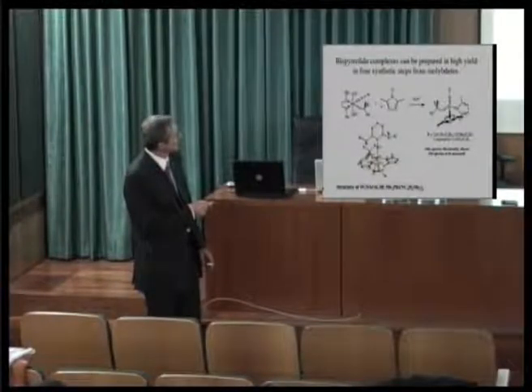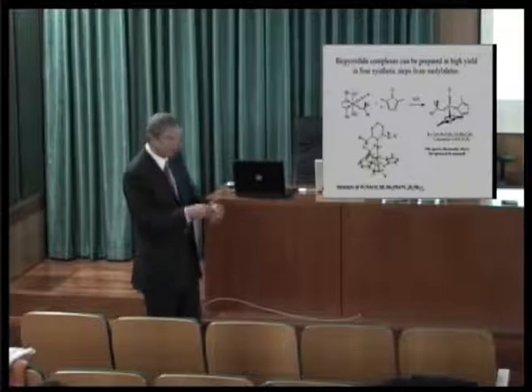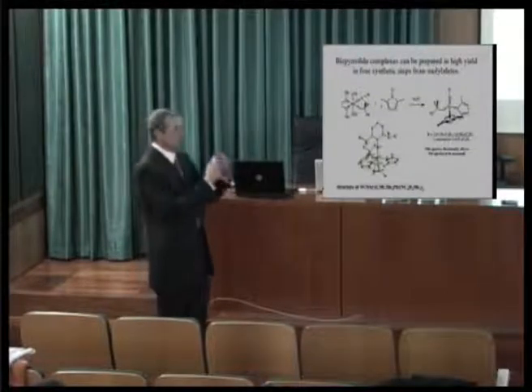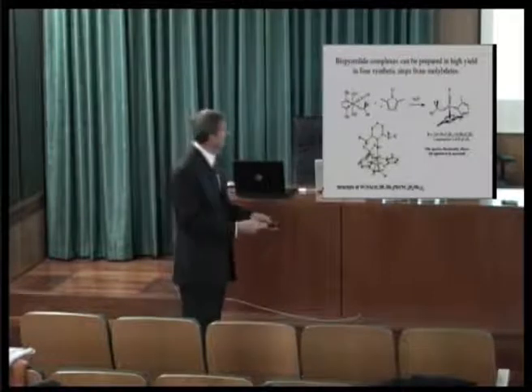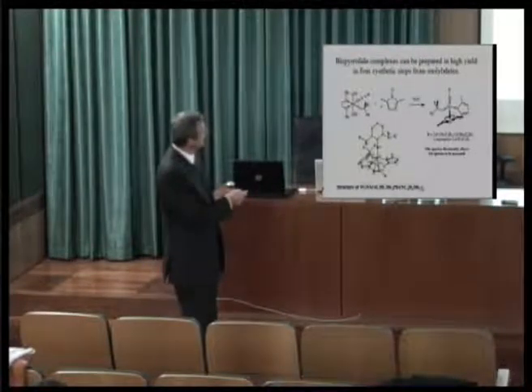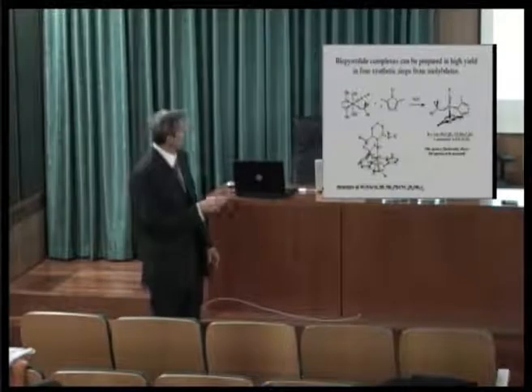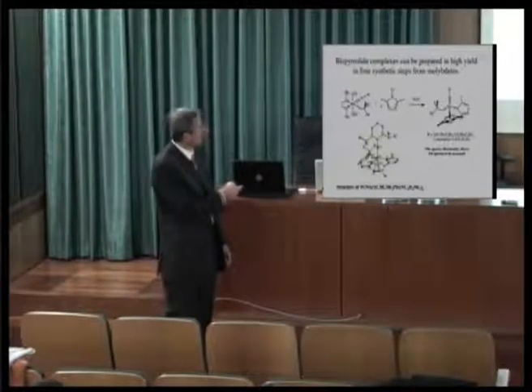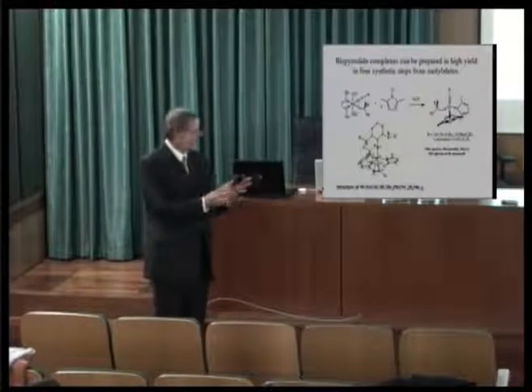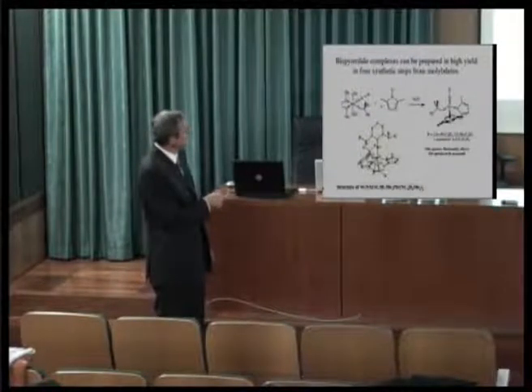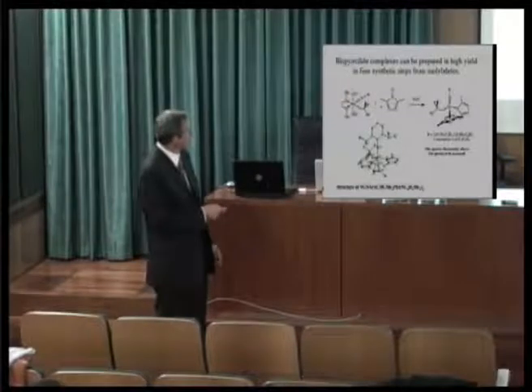And we decided it was not obvious, but it turned out to be that the precursor that would react with an alcohol, we thought, would be what is shown here. This is a bispyrrolide. This is a 1- ligand. It can be protonated by alcohols, and you can make a bis alkoxide from it, and also then in the process, as we'll see, the pyrrole, which is not a reactive species. It does not bind to the metal. So this is likely to be a good precursor to bis alkoxide catalysts.